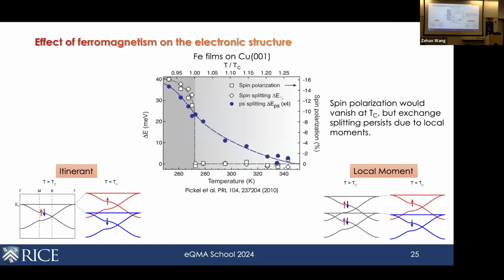Okay, just to show you some reference, this is a measurement from literature on iron film, which perhaps many people consider to be itinerant. If you measure the exchange splitting from photoemission on iron films, which are these blue dots, this is the ordering temperature. You can see that the exchange splitting only drops by about half, and it takes much more elevation in temperature to go away. Whereas they also measured the spin polarization, and that actually drops at the ordering temperature. So you can see even in iron films, there is still contribution from both. The description should really be somewhere in between the itinerant and local moment picture.